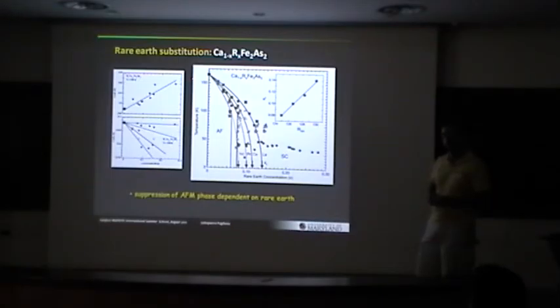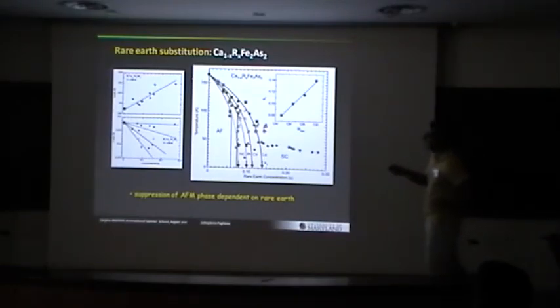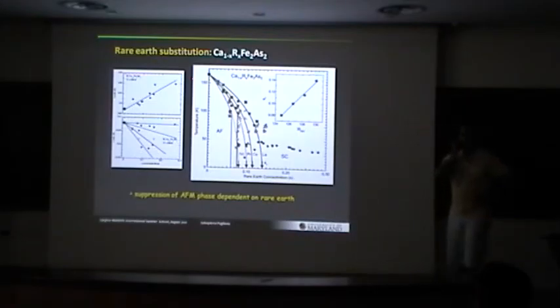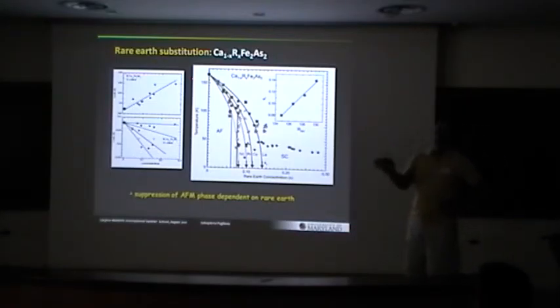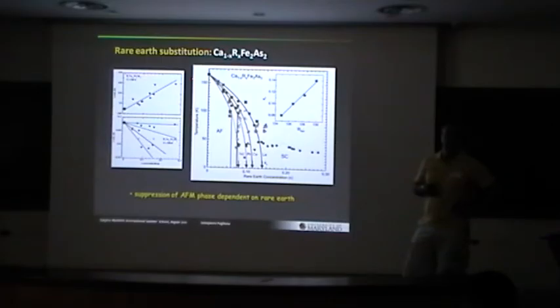A very basic question, a little bit in his direction and what you said as an answer. I only know a few of these compounds, a little bit, and everyone always talks of the antiferromagnetic phase. Is it always the same order, or are there different orders in the antiferromagnetic phase? In this phase here, or just in general over all the pnictides, the iron-based superconductors? Iron arsenides, yes. It's always commensurate AF order. There may be a bit of a c-axis component to the q vector in some cases, but it's always half-half, which is why there's a lot of discussion about nesting between the hole and electron pockets.